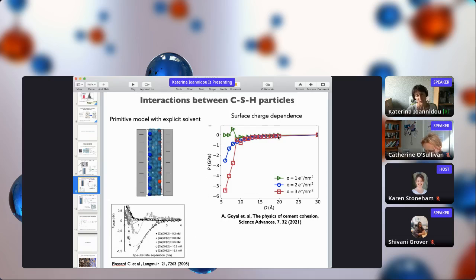This is exactly what we get here. For example, with low surface charge, we have a repulsive shoulder and an attractive well, and when we increase the surface charge, we have a very attractive well, which corresponds to the cohesion we find in cement when it's at the hardened cement paste stage.